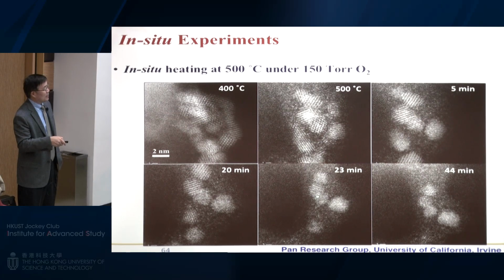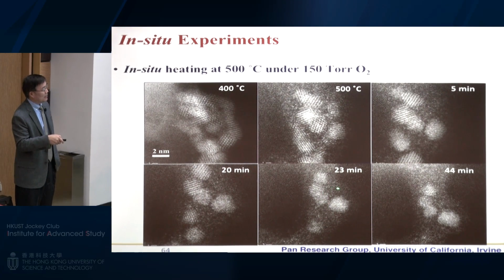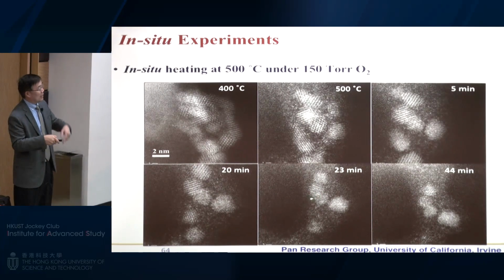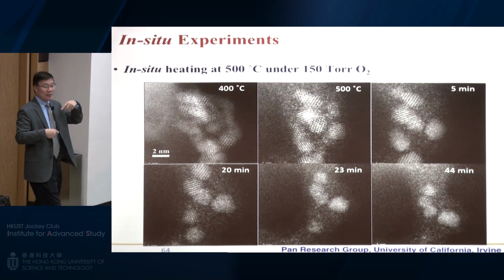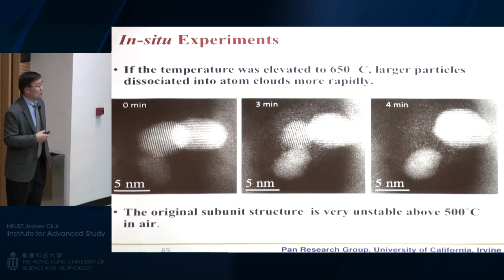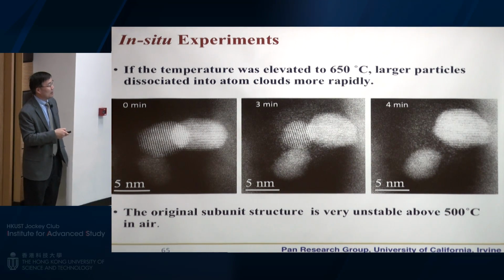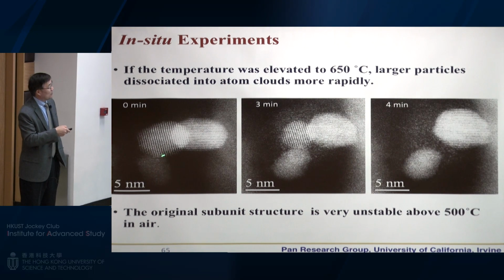But the important, surprising finding is that there are a lot of small atomic clusters forming during this process. If you replace the oxygen with hydrogen, these will disappear, and gradually the particle will grow further. You can do this back and forth. We call it a redox reaction. So this is two particles, actually three particles, 1, 2, 3, and gradually you can see that these two will merge, leaving some kind of atomic cloud here. Then this one is much smaller than the initial.